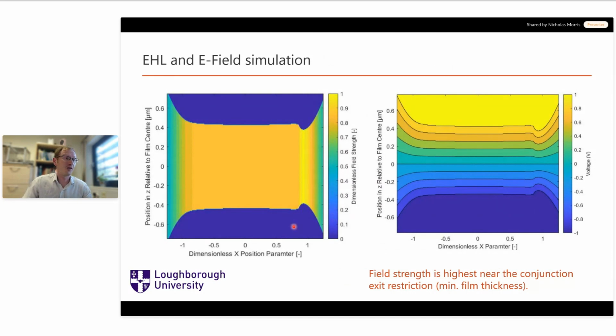Will that cause more EDM pits to form in future? So this is for a smooth surface, and this is a generic EHL model. So these blue areas here are the metallic surface where we have an idealized conductor. In the middle, we have an idealized dielectric, and the permittivity of the dielectric changes all the way across the film with the EHL fluid film pressure of the contact. So in this case, we can see that for the smooth surfaces, as we'd expect, the point where the surfaces are closest together has the highest field strength.